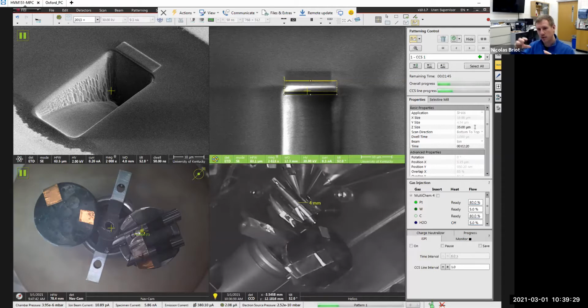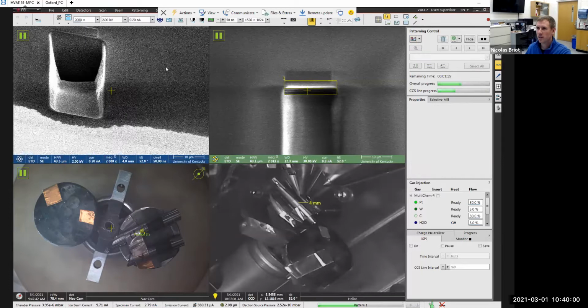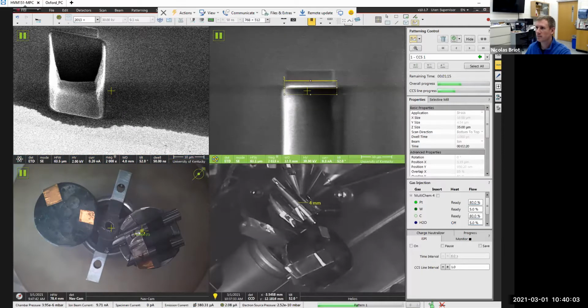So just because I know the positioning of the EDS detector relative to the sample, you will see that I will do the line scan actually on this side and not at the center or the right side, because you usually have some shadowing on the right side of the pit, because the EDS detector is on this side. So when you create X-rays everywhere, they are mostly reabsorbed here because it's blocked in the path to the detector. So that's the reason why I'll do it this way. Let's see what we have now. Okay, let's keep going. 1 minute, and then we'll do the EDS.